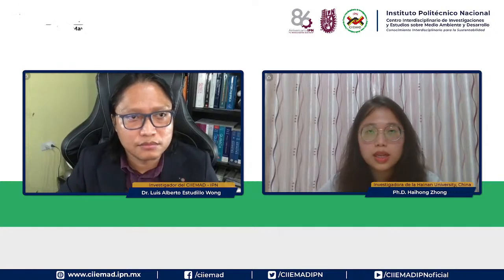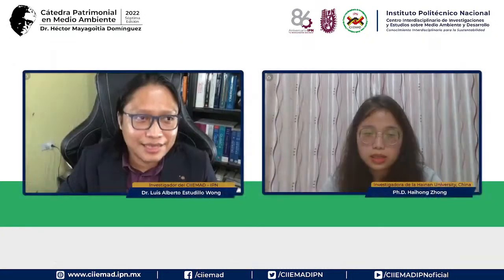Yes, in the first work the interaction with the carbon is not so good because we mixed by physical mixing. And then the second work is the cobalt nickel sulfides. Why we choose another material to get into the interlayer region is because after carbonization it can transform into the carbon. That means they are mixed by chemical connections. And the last work we are also doing is growing on carbon paper or nickel foam to improve their stability when we use it in water splitting. It will be good for the stability to grow directly on the substrate.